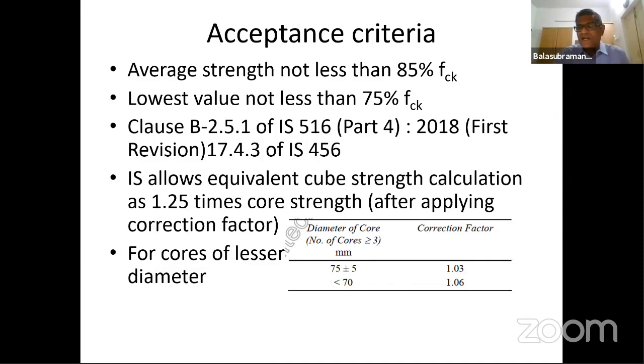Suppose it doesn't satisfy M30 grade, then you need to check whether it is satisfying M25 grade and then pass on the information to the designer. So the designer takes a final call. And then from the cylinder to cube, we apply a correction factor of 1.25. And for diameter lesser than 100 mm, if the diameter is 75 plus or minus 5 mm, then we apply a correction factor of 1.03. And if the diameter is less than 70 mm, we apply a correction factor of 1.06.